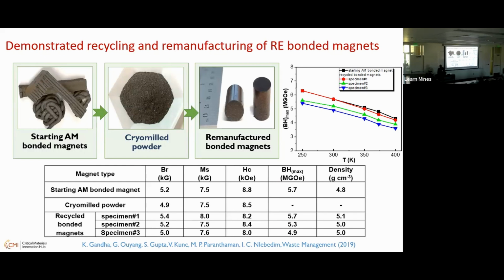And mostly we work with the non-magnetic powders. These are demagnetized powder. And once you do the printing and apply a magnetic field, the magnets have memory, magnetic power. So the moment you expose it to a magnetic field, it will align itself quickly. So that's where post magnetization, you can maintain the shape. So you can take this and remanufacture all those things we have shown in the past. And this is an isotropic magnet. And very recently, we have also worked on an anisotropic magnet, still under revision. So these are opportunities where you could do this.